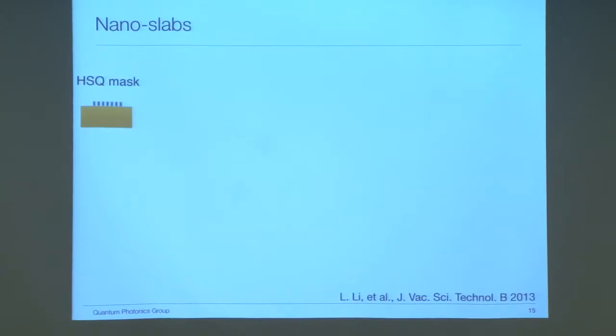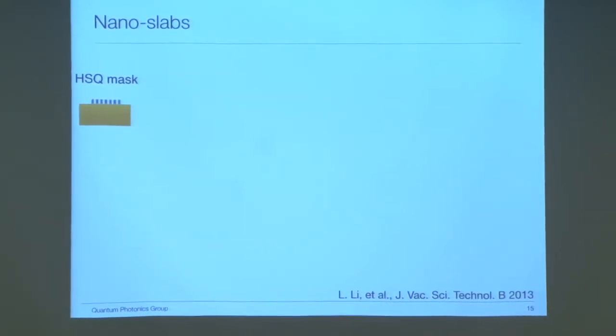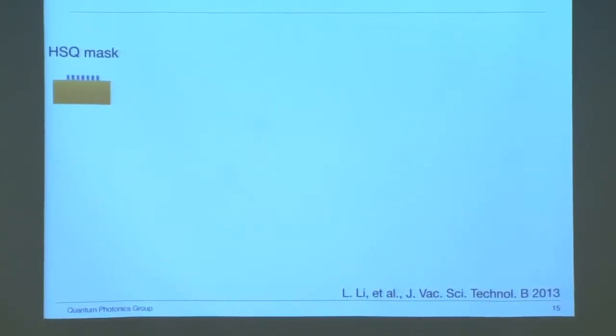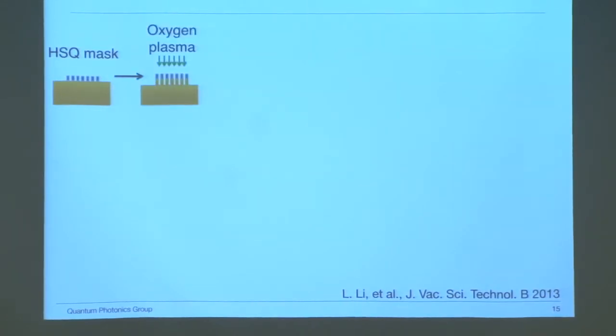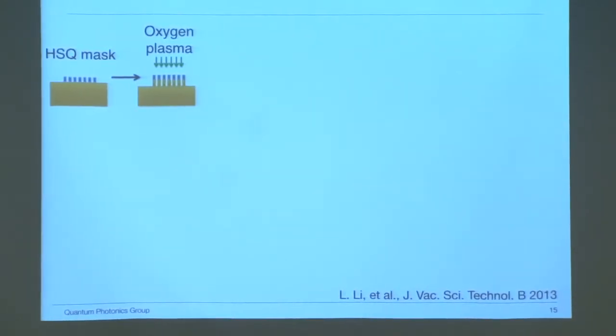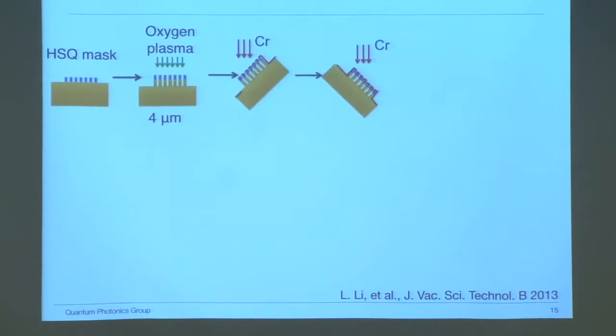We also tried a different way of fabricating vertical diamond membranes that avoids ion implantation. We first pattern HSQ strips on top of a bulk diamond using lithography, and then we use oxygen plasma to etch them down to produce vertical diamond membranes. But unfortunately, we are only able to etch 4 microns deep without degrading the HSQ mask too much. And for our applications, the deeper we etch, the better.